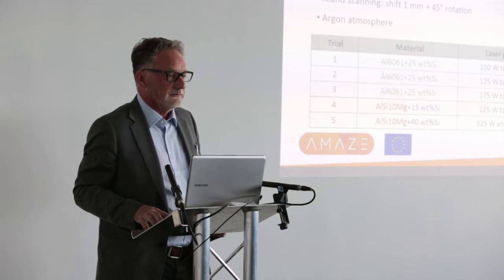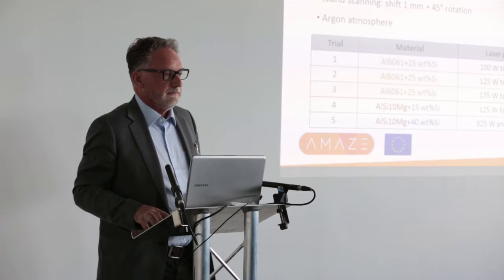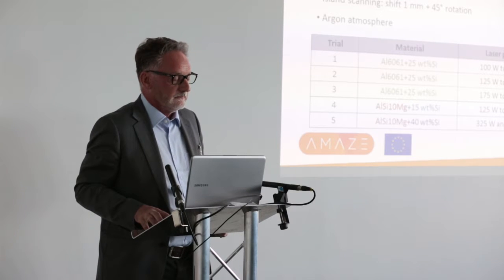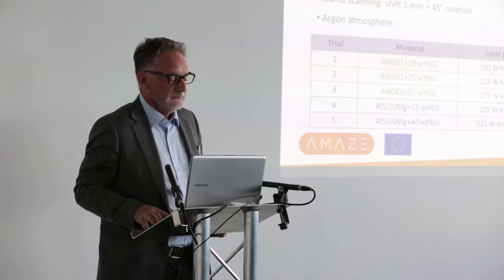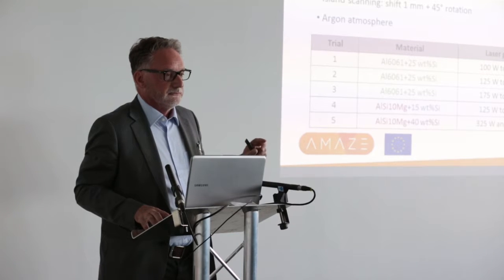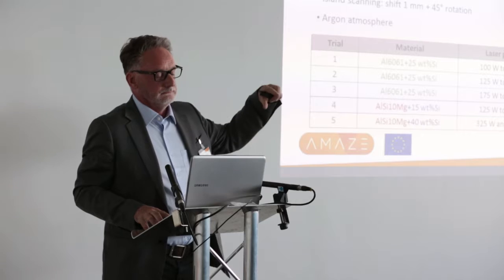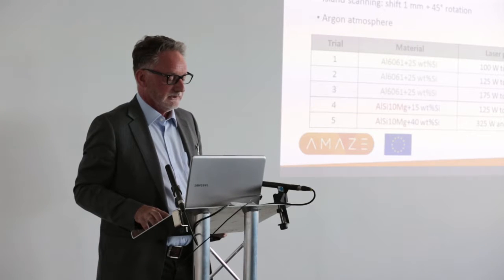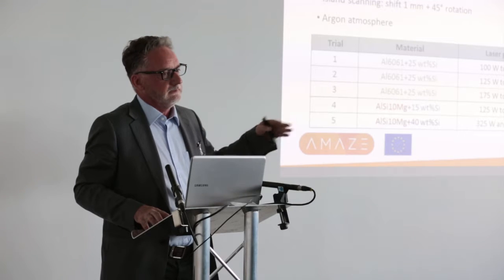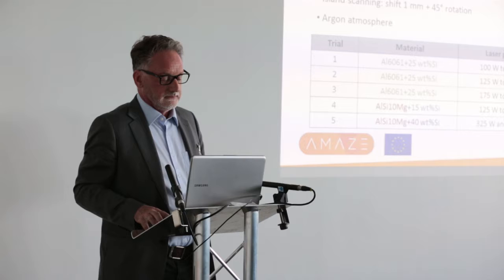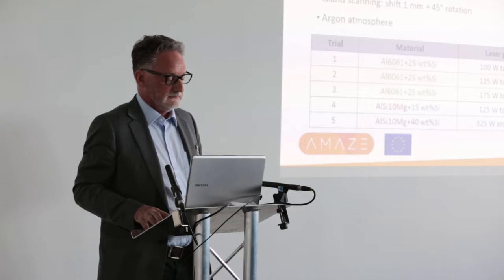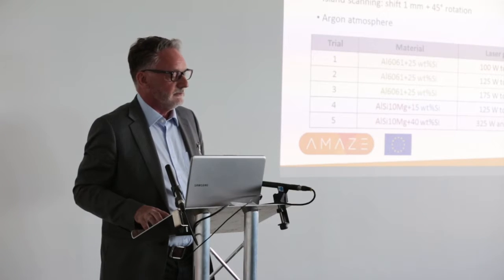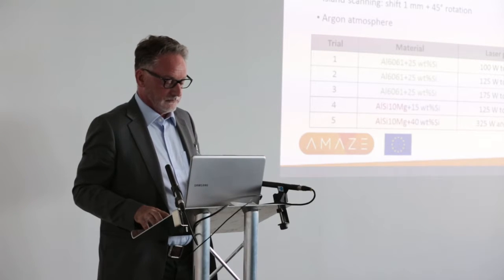So all the work was done at 30 micron layer thickness, the scan spacing 120 microns, and using the island scan, which comes with the standard processing on a Concept machine. So these are 5 millimeter squares, shift 1 millimeter and rotate by 45 degrees on each layer, obviously processing in argon atmosphere. And we did a series of trials investigating the ranges of the processing power and scan speed. So initially with the pre-alloyed material, and then with the aluminium silicon with 15% silicon added, and then with 40% silicon added in.